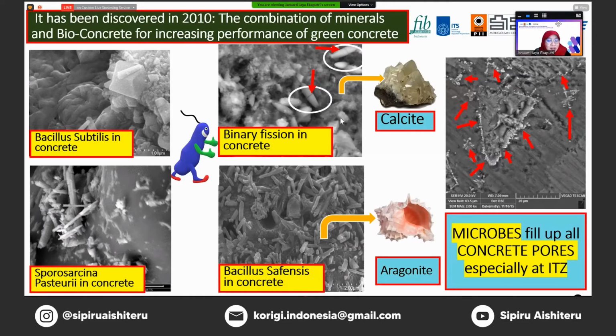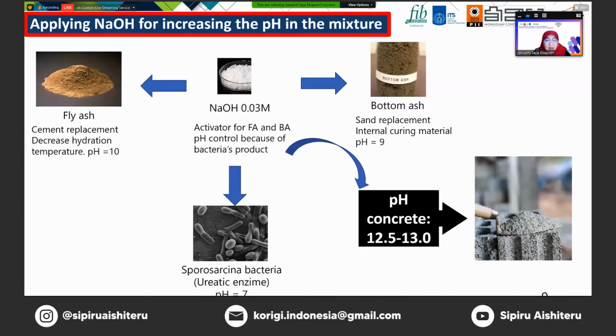We have also another innovation, using sodium hydroxide to increase the pH of concrete. Usually cement contributes to a pH of 12.5 to 13 in concrete mixtures during casting. Using fly ash and bottom ash, and bacteria, may decrease the pH in concrete. So we use a very low concentration of sodium hydroxide, 0.03 molar, introduced during the casting as a water substitution. It also increased the reactivity of fly ash.